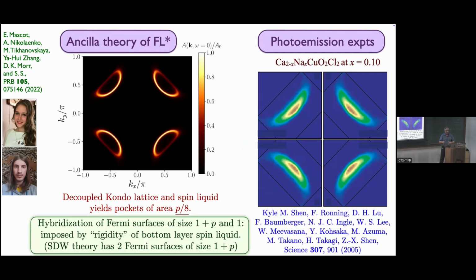And why is it p over 8 versus p over 4? If you're doing a spin density wave theory, you'd be hybridizing 2 Fermi surfaces, the original Fermi surface of size 1 plus p, and one shifted by pi of size 1 plus p. Here it is different. One of them is 1 plus p, the other one is 1. And that's what gives you in the end p over 8.